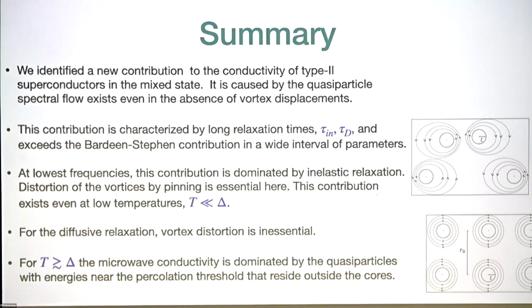Okay, so let me just summarize. We discussed microwave absorption, which arises from processes caused by the spectral flow of quasi-particles and associated with long relaxation time, either inelastic relaxation or the diffusion time across the vortex plaquettes. And for the inelastic relaxation, you need vortex distortion. And also I want to comment that although I discussed high frequencies, the same inelastic contribution due to vortex distortion also occurs at low frequencies. And for the diffusive contribution, you don't need vortex deformation.